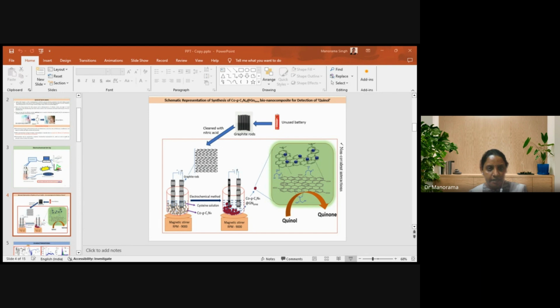Through the Raman and XRD, we easily got that yes, there is a formation of the nanocomposite. Then further, we have studied with XPS. In the survey spectrum, we can see different elements are present: sulfur from the cysteine molecule, nitrogen from graphitic carbon nitride, carbon, oxygen, cobalt, all elements are present. Further, we studied the carbon 1s, through which we can see C=C and C-N, and in the N 1s convoluted spectra of the XPS, we can see the presence of C-N=C, which is in graphitic carbon nitride, and C-N at 400.6. These are the characteristic binding energies for particular bondings, through which we can easily say that the formation of the nanocomposite has been done.